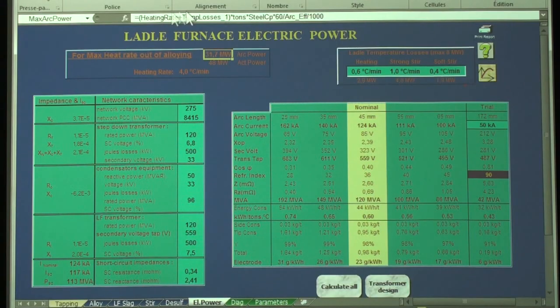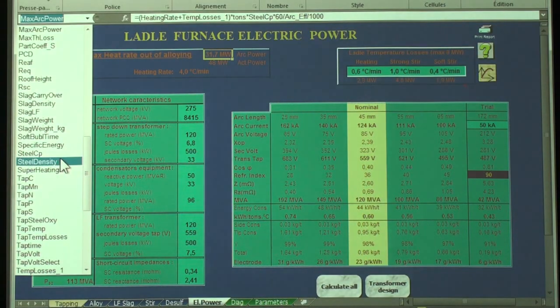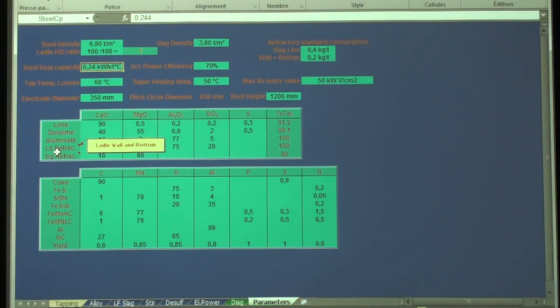But this is the model, the way the model is calculating. This is the arc power you need to develop by the arc. So you take the heating rate plus the temperature losses. Temperature losses is considered as 0.6 degree per minute for this big ladle, times the tons, times the steel heat capacity. The steel heat capacity is 0.24 kilowatt hours per ton per degree C.